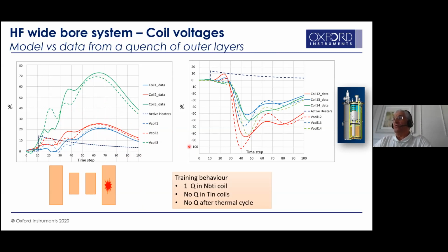And in this particular new class of high field magnets, we only had one spontaneous quench in a niobium titanium coil with no quench in the tin coils at all. And after a thermal cycle, we haven't seen any quench. That represents a major step in the management of these superconducting magnets, especially tin coils, where you can now process them and ensure that they survive a quench with no training behavior. That's one of the critical elements. In the early days of high field magnets, repeated training of the tin coils made it quite a difficult exercise to produce reliable products. Now we do that routinely.